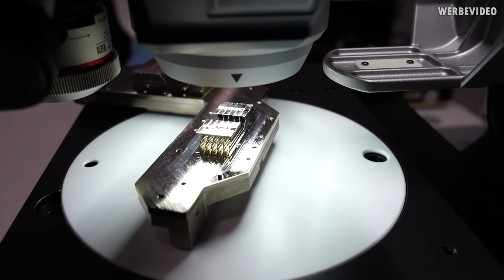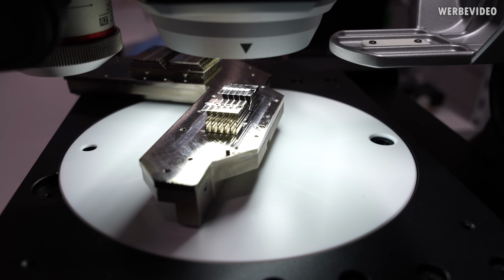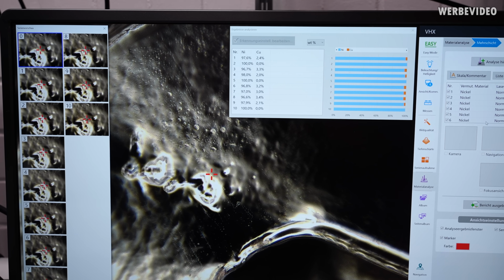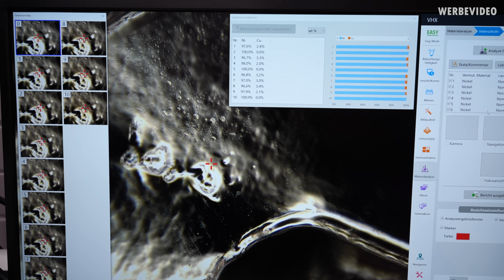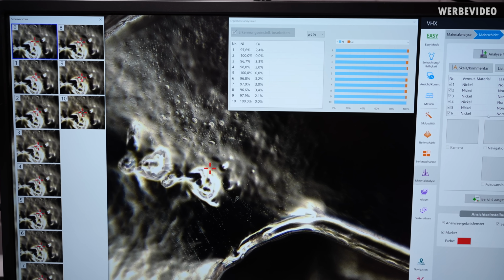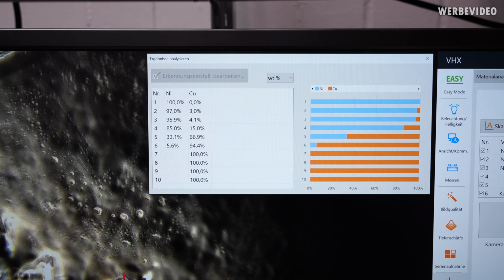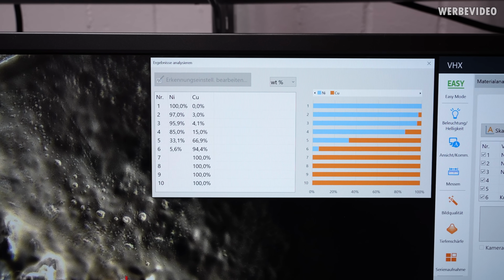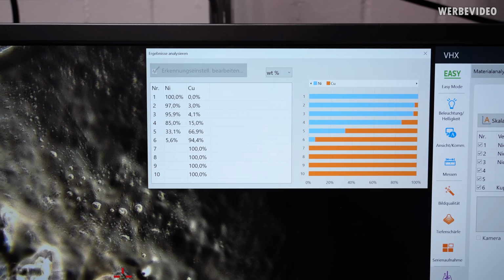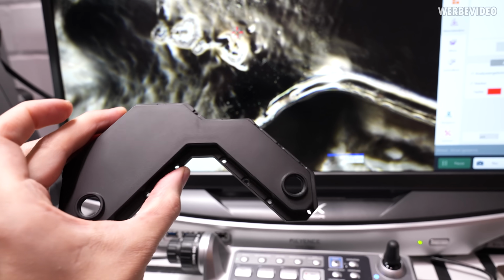The last question that remains is, what material are the fins made of? Again, very thick nickel layer, again 10 times just nickel detected, so I will just repeat it on the same spot to see if we can dig deeper. So again, same thing here, we had to just dig through the nickel layer, and underneath we can find 100% copper. Last thing to test is the case.